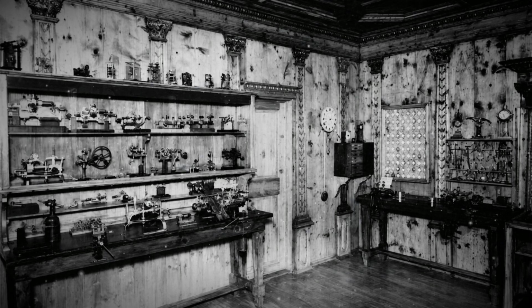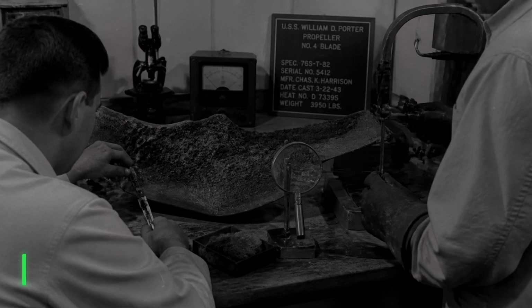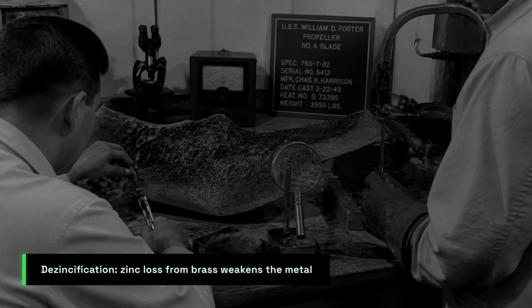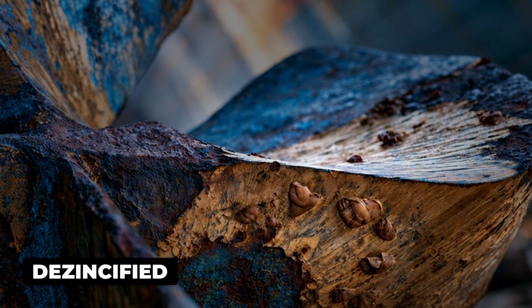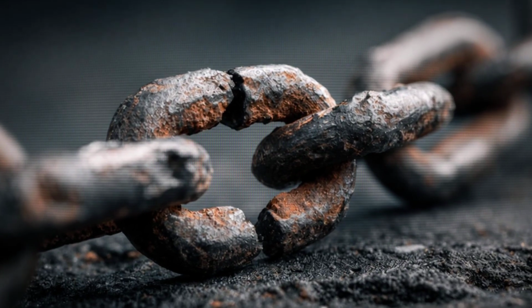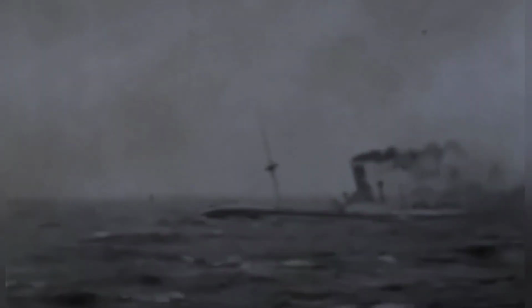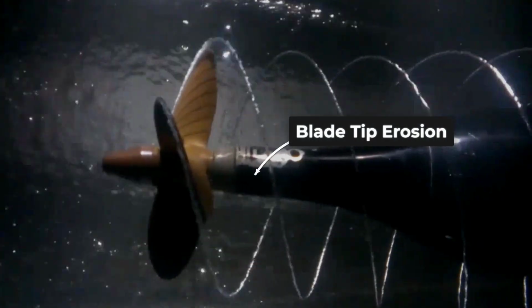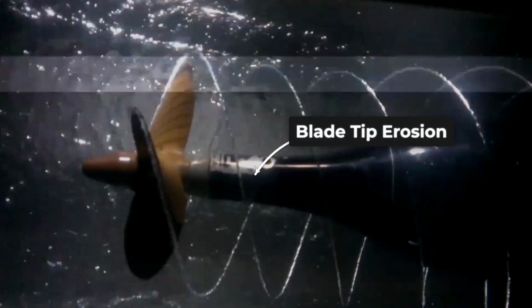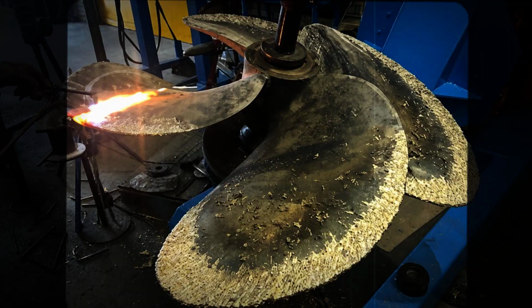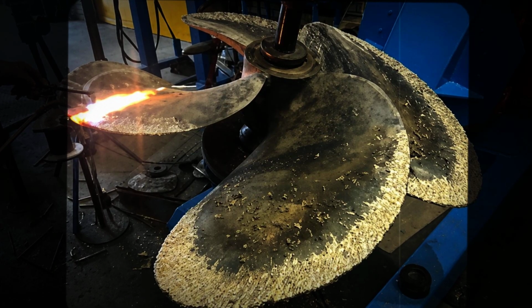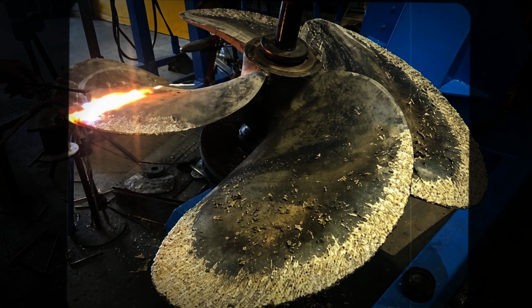In active service, these early alloys quickly revealed the limits of the older standards. Seawater systematically stripped the zinc from the brass matrix through dezincification, leaving behind a structurally compromised, spongy copper framework that easily fractured under operational loads. These failures often occurred without warning, leaving vessels stranded. Meanwhile, intense cavitation at the blade tips physically tore away the metal, drastically shortening propeller life and reducing propulsion performance.